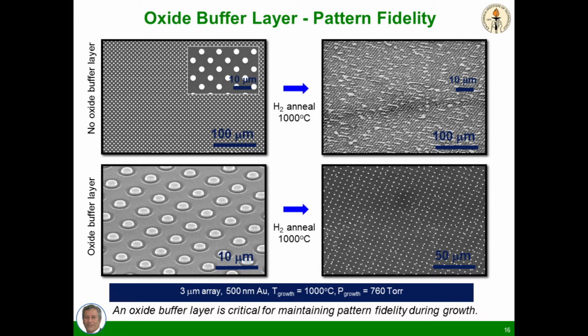The way you isolate bamboo is you put a seed into a pot and you isolate it from the next pot. And that's what we did. We etch holes in an oxide of silicon. We then evaporate or electroplate the metal in those holes. We get the right amount of metal in there because we know the surface tension of the metal eutectic on the growing droplet of a silicon microwire.